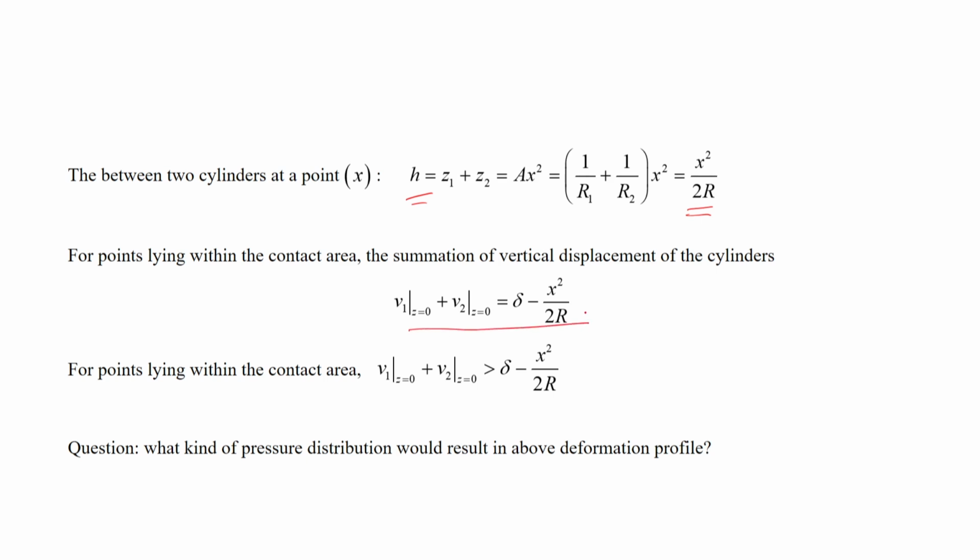This is the vertical displacement of the cylinders, the summation of that. And for points lying outside the contact area, this deformation amount is actually finally larger than this, so therefore they do not come in contact, that also we have described. Now, what kind of pressure distribution will result in the above deformation profile, that is the question.